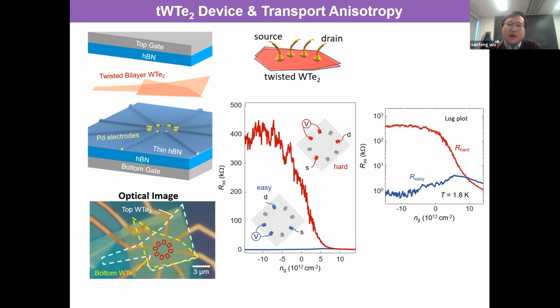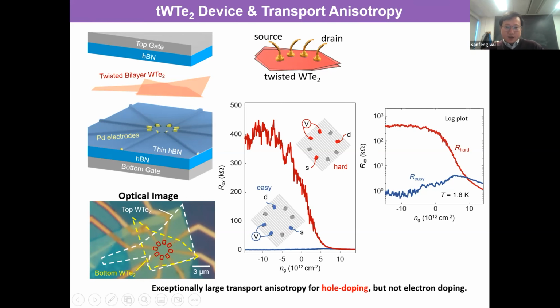What I'm showing here is the transport measurement, the 4 probe measurements, the contact configuration is shown here, along 2 orthogonal directions. One we call hard because the resistance you see here is much larger than the other direction we call easy. And in the same plot, one is a log scale, the other one is just linear scale. You can see that on the hole side, near charge neutrality to the hole side, you see a huge difference between them, about 1,000 times different. On the electron side, however, it is very close. So really, the anisotropy belongs to the hole carriers and not the electrons. Also, it's the proof, since it's gate tunable, a very good contrast experiment, that it's not because of some artifact in the device. It is the hole carrier that produces strong anisotropy.